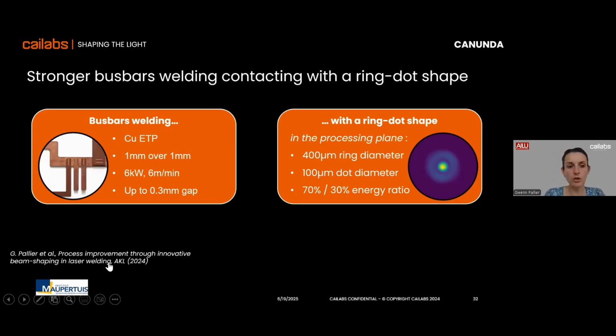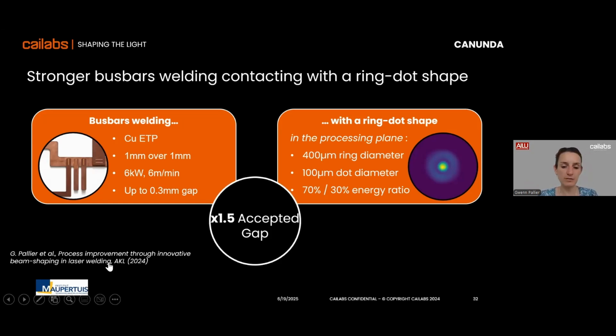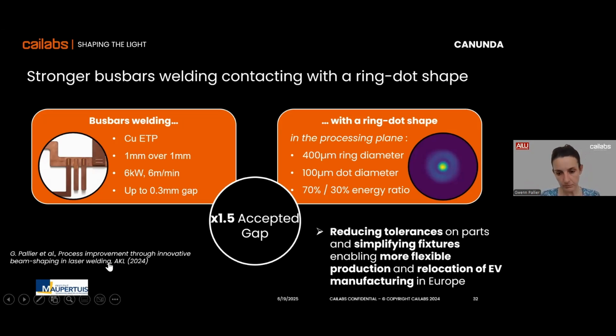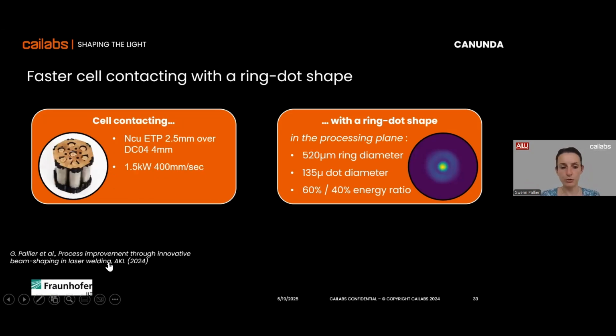But we also worked on bus bars. In the case of bus bars, we were more focused on simplifying the fixtures. The fixtures for holding those bus bars are not that easy to make. And in our case, we wanted to try to weld with gaps. Again, we stabilized the melt pool with the beam shape. And doing that, we are able to have a 1.5 times larger gap compared to no beam shaping when it comes to bus bar welding. So this is really important to enable a more flexible production.